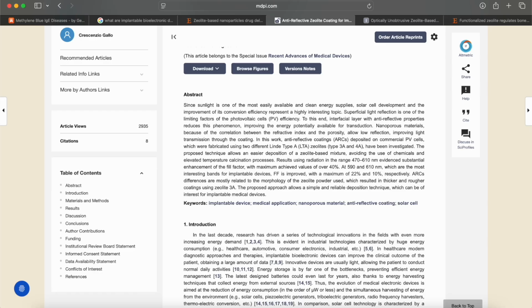Results using radiation in the range of 470 to 610 nanometers evidenced substantial enhancement of the fill factor, with maximum achieved values of over 40%. At 590 and 610 nanometers, which are the most interesting bands for implantable devices, FF is improved with a maximum of 22% and 10%, respectively. ARC differences are mostly related to the morphology of the zeolite powder used, which resulted in thicker and rougher coatings using zeolite 3A. The proposed approach allows a simple and reliable deposition technique, which can be of interest for implantable medical devices. So they are coating the biosensors with the zeolite because the zeolite is very porous.